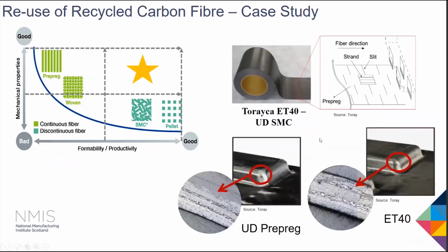So after compression molding, you can have a look at the cross sections of the composite sample. If you use the UD prepreg around this corner, you will achieve a large area of resin ridge. And if you use ET40, which contains lots of short fibers, you can see all of the cross sections are fully covered by the fibers.